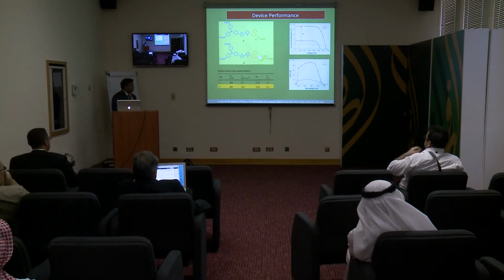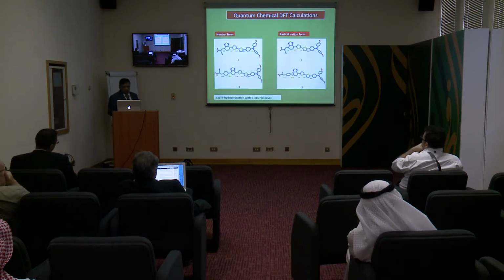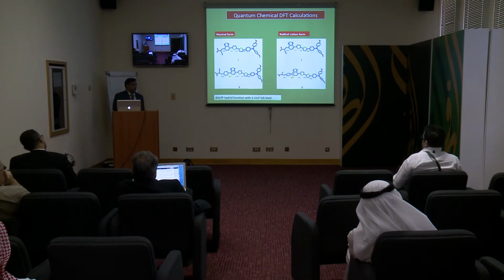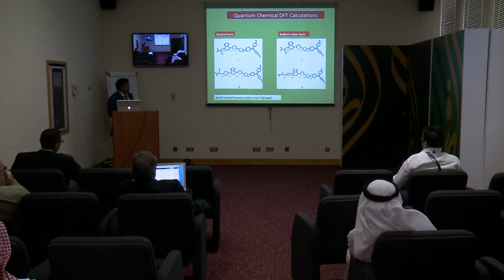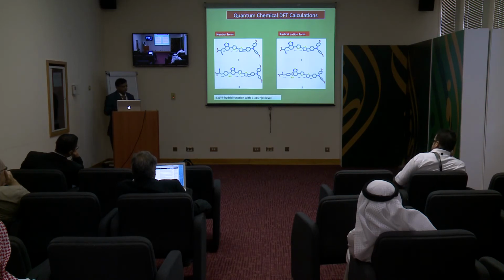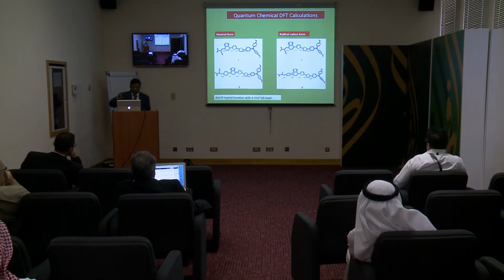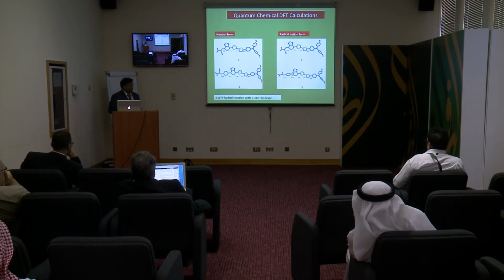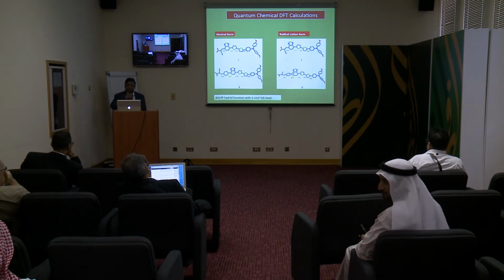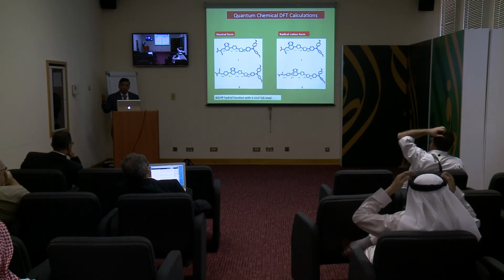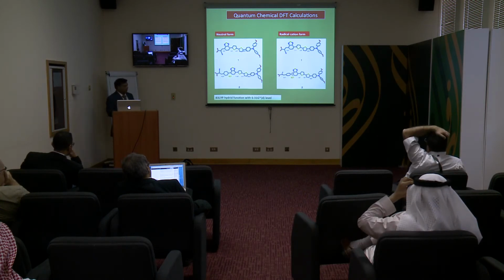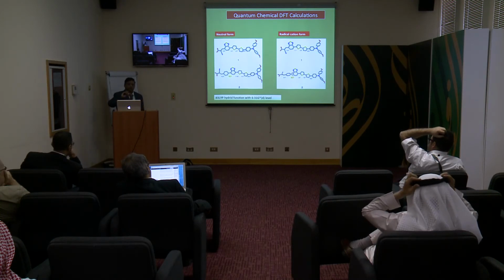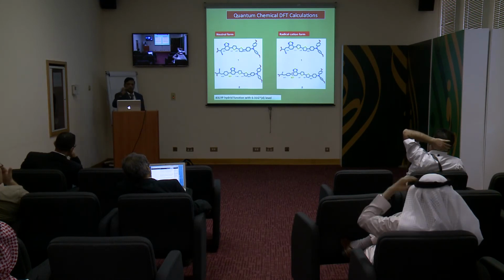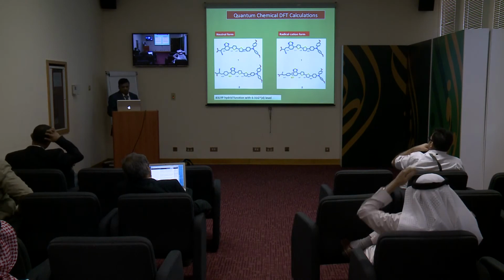To know the difference between these two molecules, the influence of the phenyl group, we did some theoretical calculations to show what is happening in the dication stage. For example, when the dye injects into the TiO2, it forms a dication. If you check the structure of the dication, it shows that the dye 1 has a planar structure, whereas the phenyl one, because of the phenyl, is tilted. So when you have this planar structure, it is injecting into the TiO2, but at the same time the injected electron is recombining with the oxidized dye very easily, whereas in the case of this phenyl group, it is tilting like a locker. It is blocking the reverse electrons. So that is the main reason why having a phenyl has such a dramatic effect.